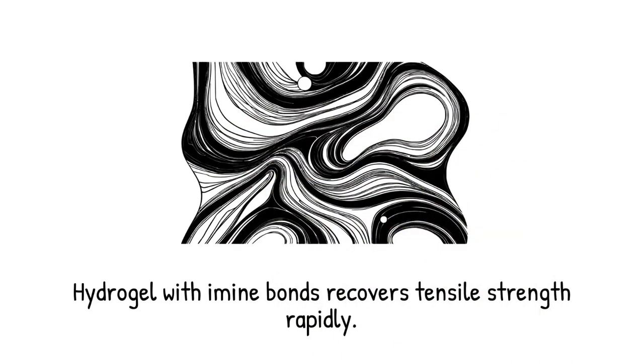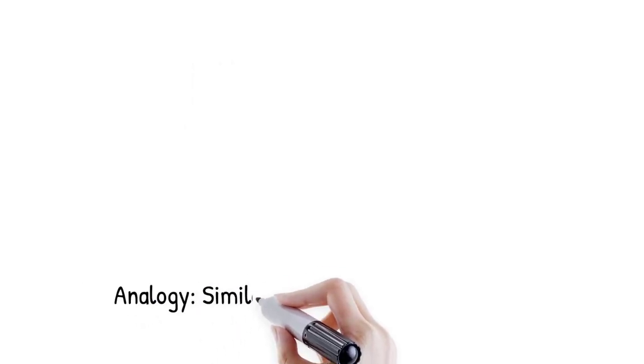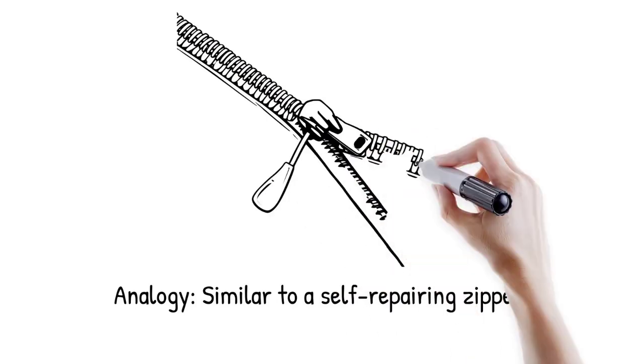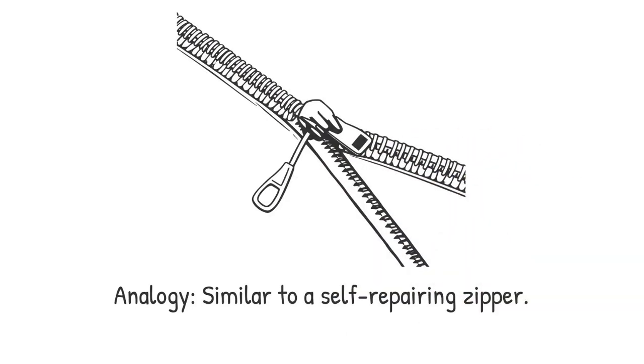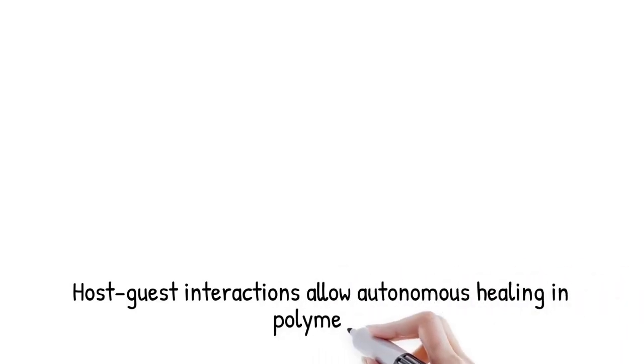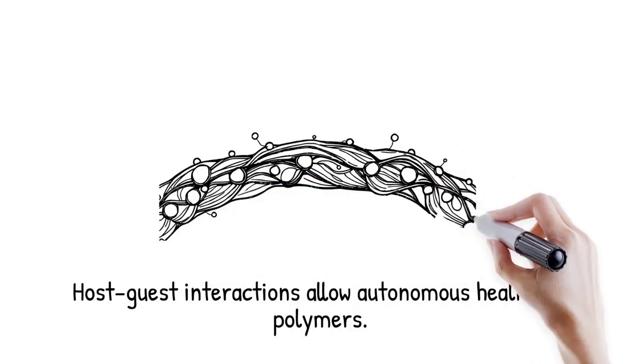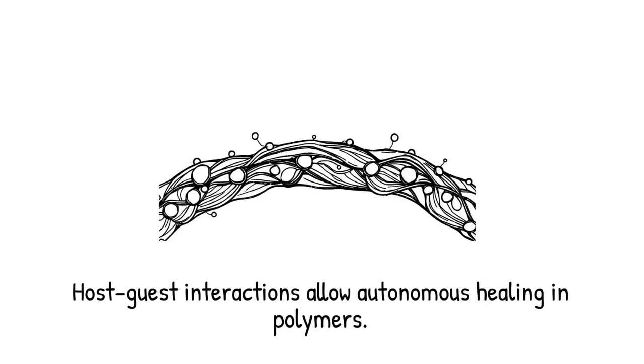A hydrogel cross-linked via imine bonds recovered 80% of its original tensile strength within 2 hours at 37 °C after being severed. It is like a zipper that unfastens under tension, but zips itself back up when you realign the teeth. Weak non-covalent host-guest interactions, such as cyclodextrin-adamantane complexes or metal-ligand coordination, enable reversible cross-linking and autonomous healing.